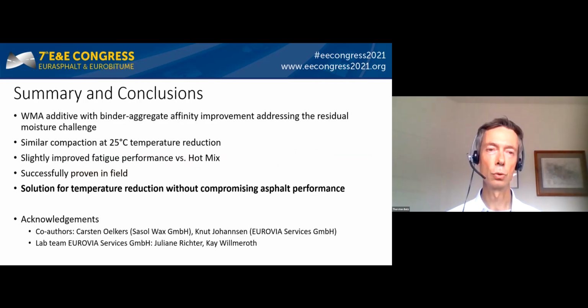Finally, my summary and conclusions. A Warmix additive with binder aggregate affinity improvement was designed, which addresses the residual moisture challenge. It allows similar compaction at 25 degrees lower temperatures. The fatigue performance of the asphalt was slightly better compared to the reference hot mix asphalt. Meanwhile, this concept was successfully proven in field tests. So in summary, a solution for temperature reduction without compromising asphalt performance was developed.